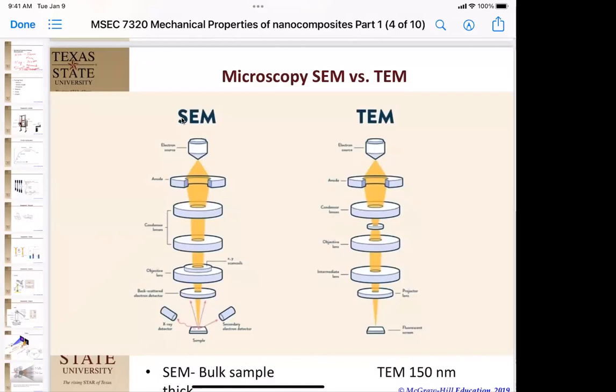Last general question: why do we coat the materials with gold and palladium before the SEM? You don't have to. In the old days, we did that because you want as many of the electrons to bounce off as possible. Some of the sources used to be like 30,000 electron volts, which basically eats through things that aren't metal. That's the first reason. Second reason is you want to dissipate the electronic charge that builds up on your sample too. So if you have a conductive grease or a semiconductive material, you don't need to put metal on there if you run it at a low enough voltage. Usually if you run it under about 5,000 volts, you don't need to coat it. In fact, I think there's even environmental SEMs that are running closer to atmospheric pressure. You also don't need to coat it.